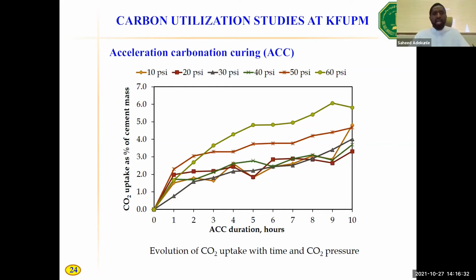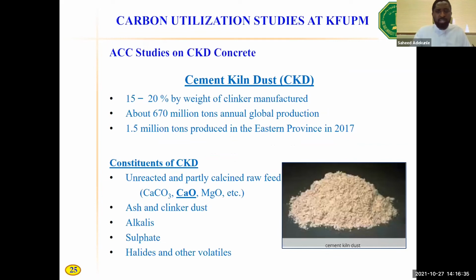So in addition to this study, recently we also conducted another study. As was shown previously, CKD is a major byproduct of cement manufacture, and CKD is highly alkaline. For every kg of cement manufactured, you have about 150 grams of CKD coming out. So CKD was incorporated in concrete here at KFUPM, and we tried to use this to enhance the carbon uptake in concrete. Because CKD is highly alkaline, it will help to combat the possible challenges of de-alkalization.